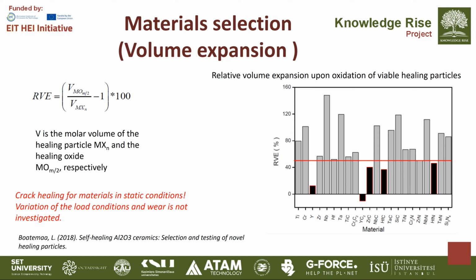When a crack forms in a ceramic composite, as we showed earlier, the embedded healing particles located near the crack path are exposed to oxygen or another oxidizing environment at elevated temperatures. The particles undergo a chemical oxidation reaction, producing an oxide phase that has a higher specific volume than the original metal or compound, like titanium carbide or nitrides, etc. The newly formed oxide expands and fills the crack cavity, restoring structural continuity and preventing further crack propagation.